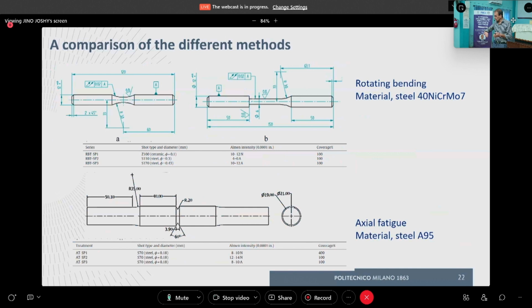And then let's conclude, and I will not take much more time after the official end of the lecture, with a comparison of the different methods we did. We have used 3 different geometries. You see here the smooth geometry, the usual hourglass sample. This is a notched bar, with a small fillet radius, with K_t around 2. The material is a low alloy steel, 40 nickel chrome molybdenum 7, and the applied load is rotating bending.